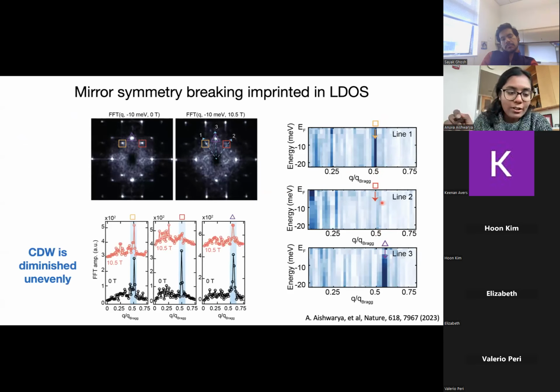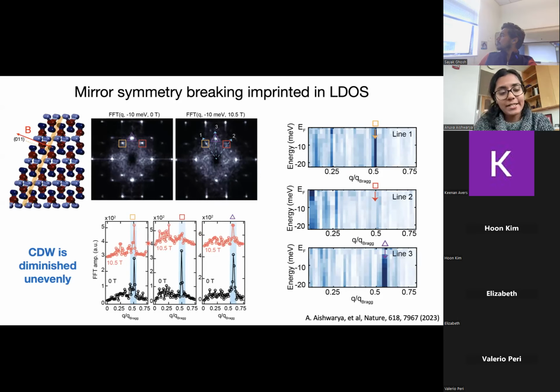Some more line cuts show that all components of the CDW are suppressed in magnetic field. However, one of them is much more suppressed than the other two. This is not very surprising because the magnetic field that we're applying is along this strange direction, and this magnetic field actually also breaks mirror symmetry. But what is surprising is that the CDW is responding to this magnetic field at such small fields.